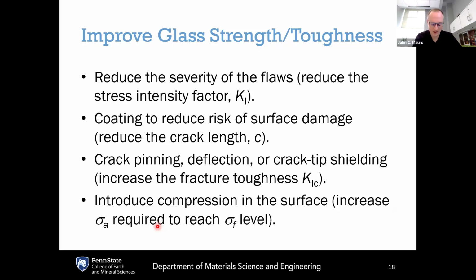How can we actually improve the glass strength and toughness? There are several different ways to do that. One is to reduce the severity of the flaws. So how do we reduce the stress intensity factor K1? Another way would be having a coating to reduce the risk of surface damage. So this would aim to reduce the crack length, C.